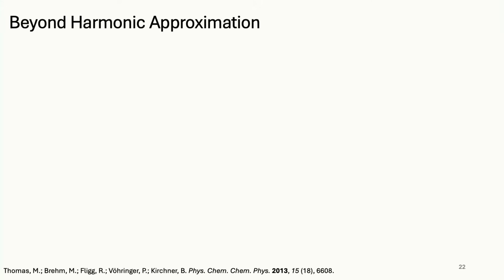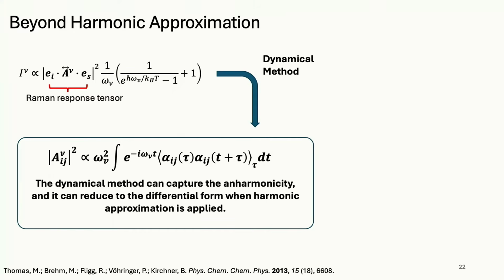And we were able to take a first principles calculation. So we're using quantum mechanics and saying, what are the forces on all the atoms? What are all the vibrations? But here's the key. We didn't just calculate the phonons. I'm sure you're familiar with the idea that you can do a Taylor series of the energy and calculate the vibrational modes. We didn't just do that. What we did was we said, let's do a real molecular dynamics study. Molecular dynamics isn't limited to a quadratic approximation. It visits all the structures that the material might actually visit. And then we do what's called a polarizability autocorrelation function. And this is a way to get the real Raman spectrum, not just from the harmonic modes, but from everything.